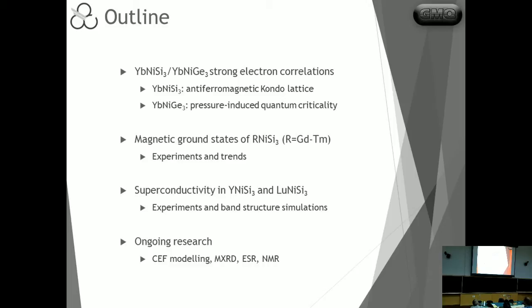Then, a long way forward, already back in Brazil, we started working on characterizing the rest of the series of the magnetic rare earths. And then finally, just very recently, when we looked at the non-magnetic rare earths, we discovered a couple of new superconductors here. And if there's still enough time, I might talk a little bit about some of the ongoing research that we've been doing as a consequence of these things here.